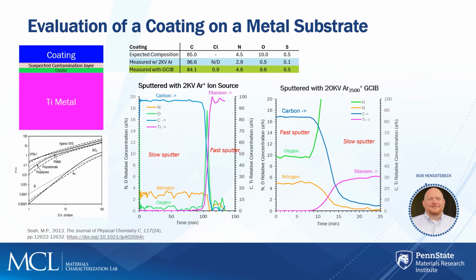When we go to the GCIB source, now all of a sudden, we're actually sputtering that coating much faster. This is something that's uniquely found about these GCIB sources. They sputter organics very quickly, where the inorganics sputter very slowly. That's shown in the bottom right image there. And in fact, if you were to ratio one to the other, the organic portion to the inorganic portion, what you would find is that organics are sputtering at anywhere from 1,000 to 10,000 times faster than the inorganics.